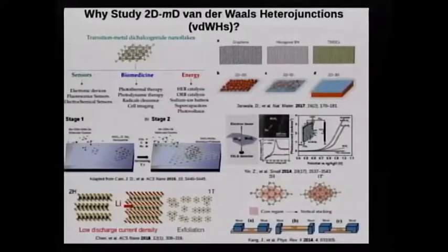So I have selected here two very used methods. One is the chemical vapor deposition, in which you begin with the molecules being formed in the gas phase, and then you form your nanoflake, which is a bottom-up synthesis example. But if you have your bulk material, like in here, you have a trigonal prismatic 2H phase, and then you can adsorb lithium in solution, and then exfoliate that with an electrical current, and you can obtain nanoflakes of, in this case, 1T octahedral nanoflakes.